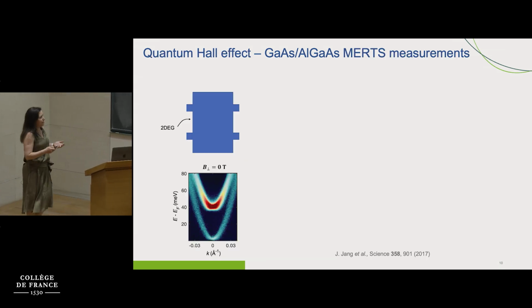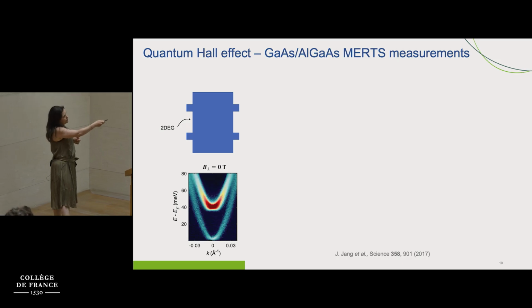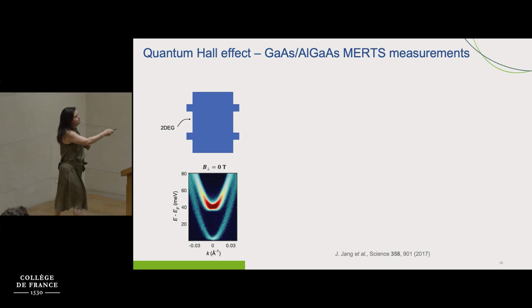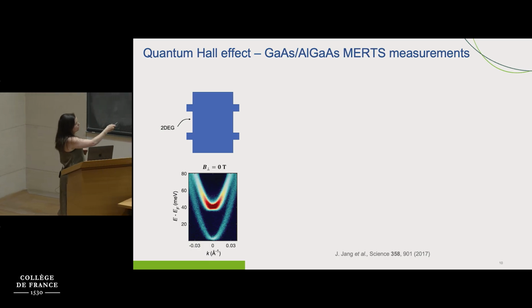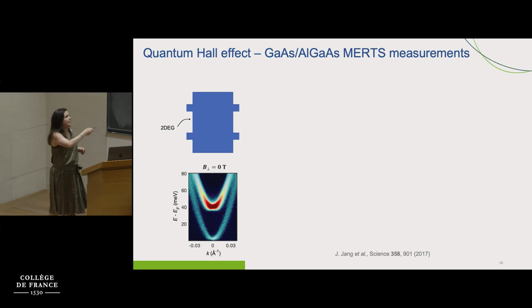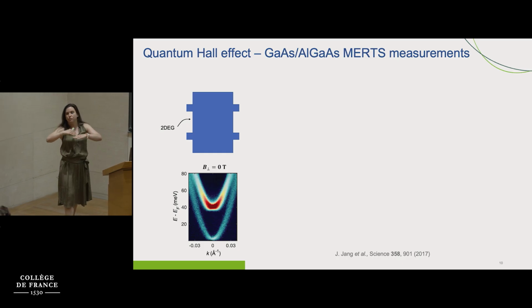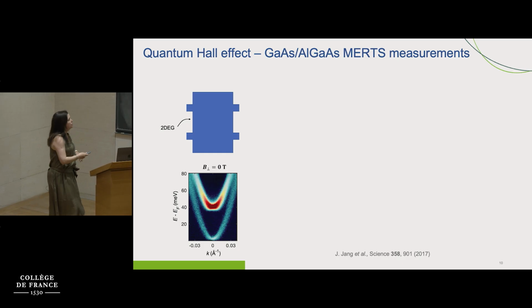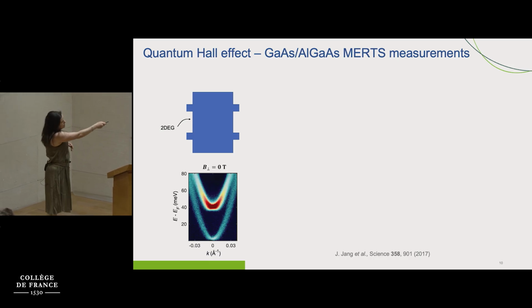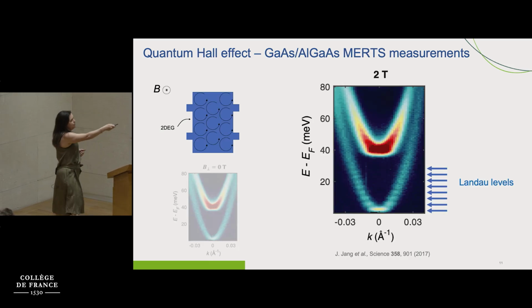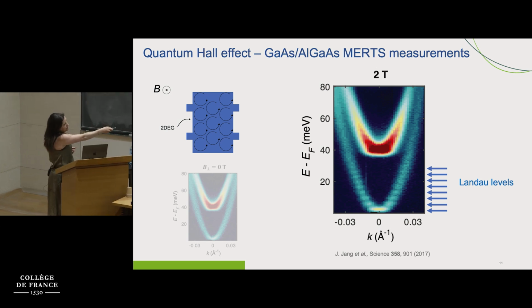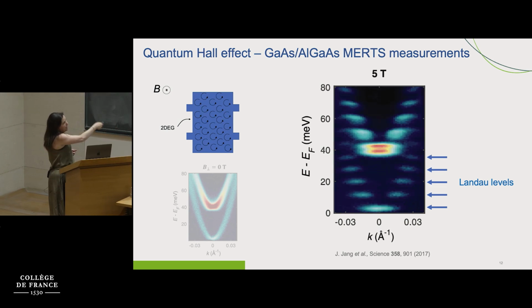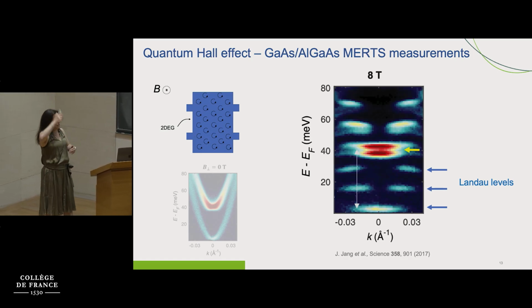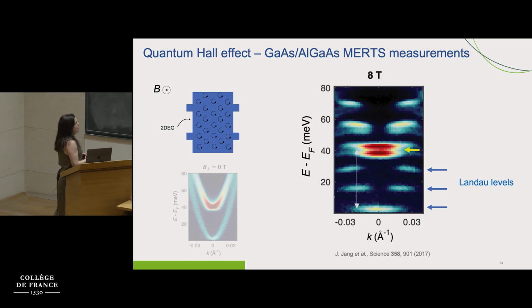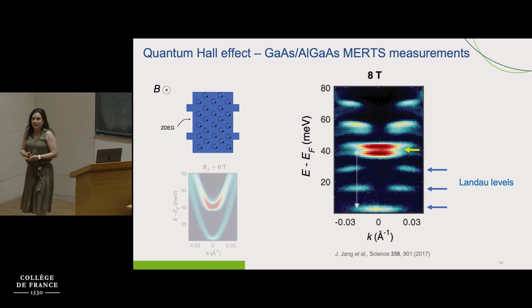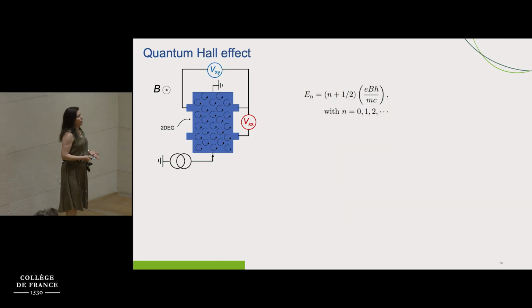So in a two-dimensional electron gas like gallium arsenide, we have a parabolic energy dispersion. These are, in fact, momentum and energy resolved tunneling spectroscopy, because unfortunately in gallium arsenide, as this is a buried structure, we cannot perform ARPES like the ones that Antoine showed before. So you can see that we have a parabolic energy dispersion, and as we apply the magnetic field, we're going to see that this energy dispersion splits into Landau levels. And as you increase the field, the splitting between Landau levels becomes larger and larger, okay? And that, of course, is going to have consequences in what we are most interested in, the quantum Hall effect, okay?